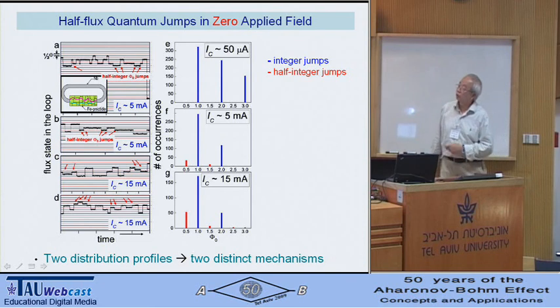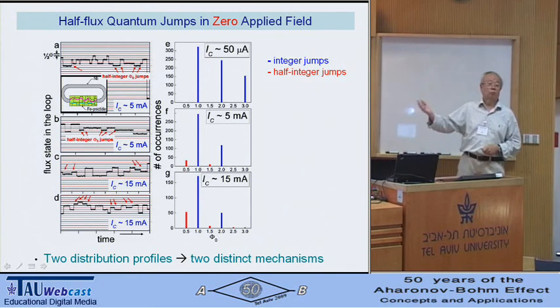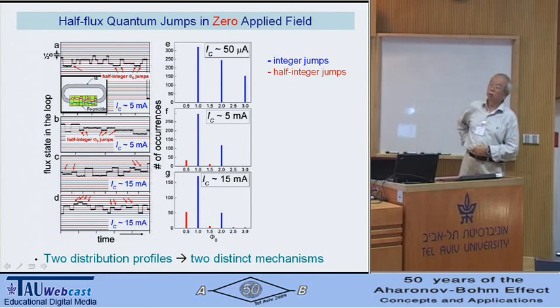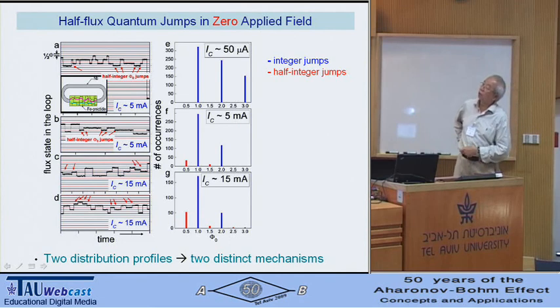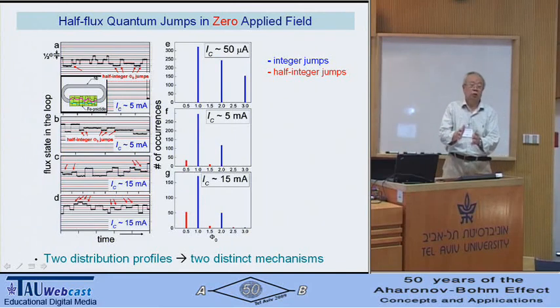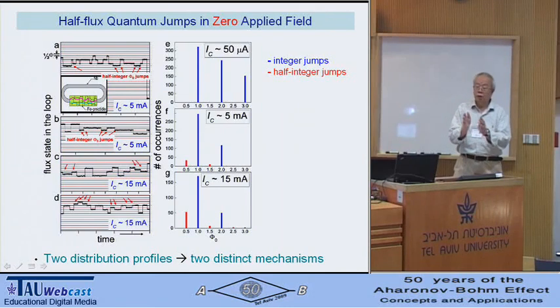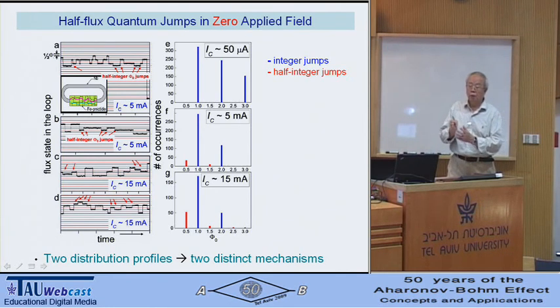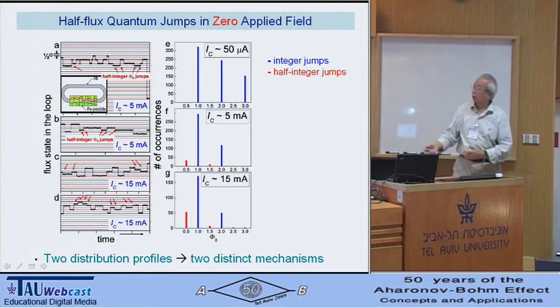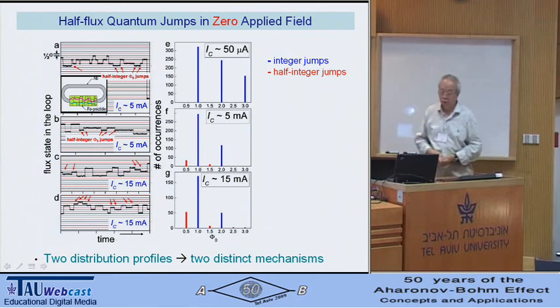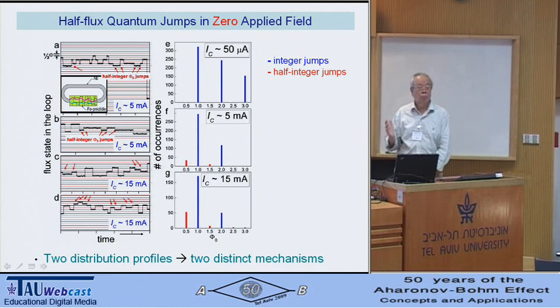Okay, here's a summary of the result as a function of coupling strength. Since we observe hundreds of such flux quantum transitions, let's plot a histogram to see. When the current is like this, you have only the integer flux jump. Now, when you increase the current, you push the point contact a little bit harder, then you start to see the half flux quantum. Push more, you get more. But clearly, you see there are two distribution profiles. In other words, they're different. They're not just one story. There are two things. And that's consistent with what I just discussed. You need to switch paths to see half-flux quantization. So the red and the blue here represent two different paths. So it's highly suggestive, but I don't have a hard proof of it.